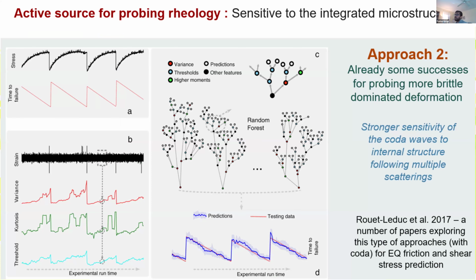And again, this idea of looking at details of the coda is not new. There are a lot of people on this call, and a number of people have been looking at these kinds of approaches for more brittle dominated deformation. This is one of the classic papers from 2017, which looked at earthquake friction and asked, what is the time to failure? If we have continuous active source data, we can look at the changes occurring in the structure of the waveform and use that to come up with a prediction. But that's primarily in the brittle dominated regime.